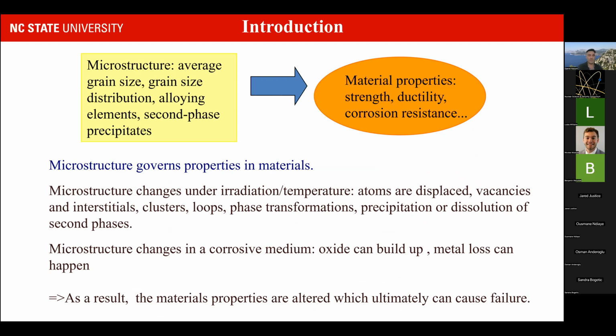By microstructure, we talk about average grain size distribution, alloying elements, second phase precipitates, etc. And those are the features that are going to govern the mechanical properties, strength, ductility, and the chemical properties, corrosion resistance, etc. When we put the material in the reactor and it's subject to irradiation and temperature, a lot of things happen to the microstructure. The atoms are displaced, vacancies and interstitials are produced, they can cluster, grow into loops, grow into dislocation networks, phase transformations can happen, precipitation or dissolution of second phases can happen. And when it's coupled to a corrosive medium, you can have an oxide buildup or metal loss, depending on whether you are in a passivating system or a non-passivating system, such as in molten salt reactors. So as a result, the microstructure changes, and therefore the material properties are going to change.